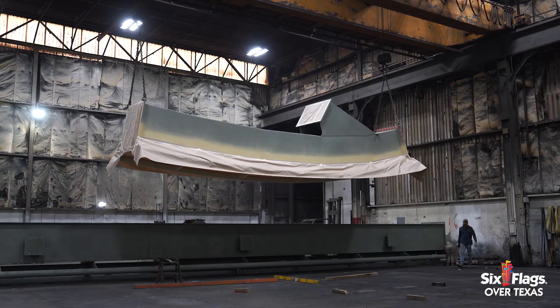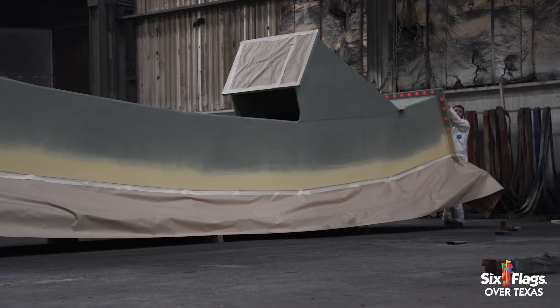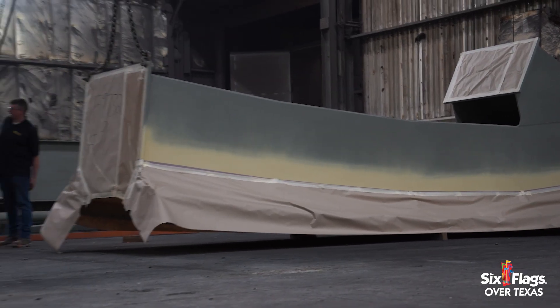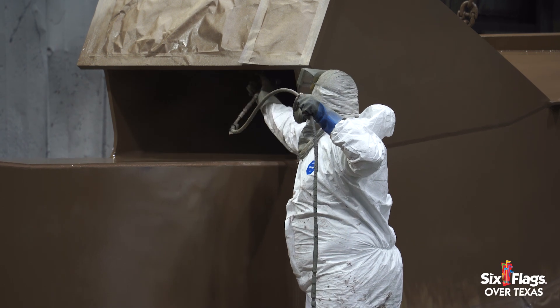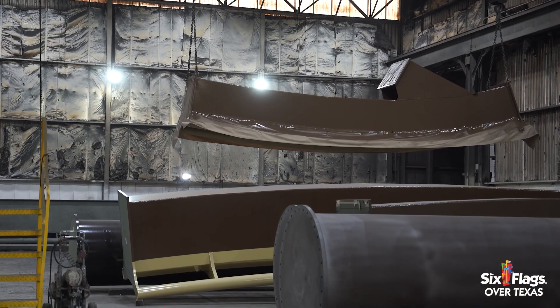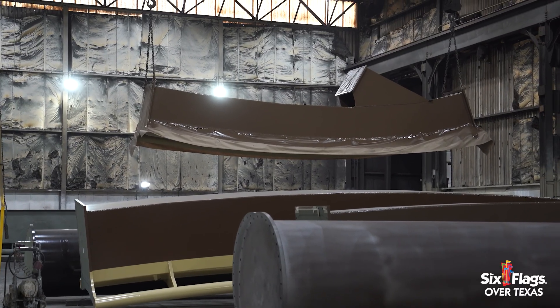Painters painting track today is a unique paint system. It's a two-tone system, and it starts with a zinc epoxy primer on top of blasted steel. Then we sand that primer and apply a two-part urethane on top of that. It's a highly sophisticated industrial coating that's going to provide years and years of protection in the field.